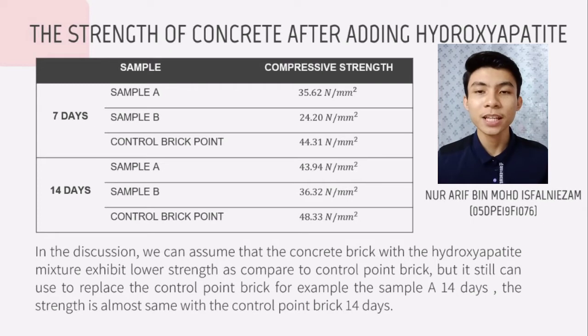For the 7-day sample A, the compressive strength is 35.62 Newton per millimeter square. For the 14-day sample A, 43.94 Newton per millimeter square. Next, for sample B 7-day, 24.2 Newton per millimeter square. For the 14-day sample B, 36.32 Newton per millimeter square.